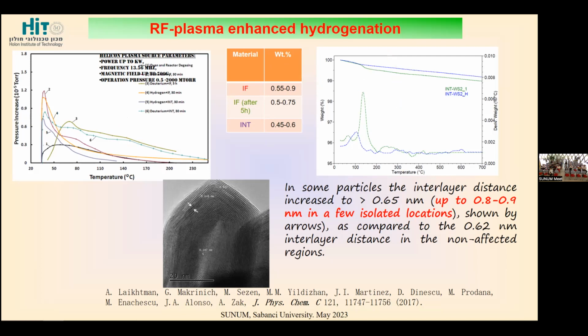By the way, TGA confirmed that our nanoparticles become hydrophobic, which is very good for applications. Otherwise, they absorb a lot of water in air, which is not very beneficial.